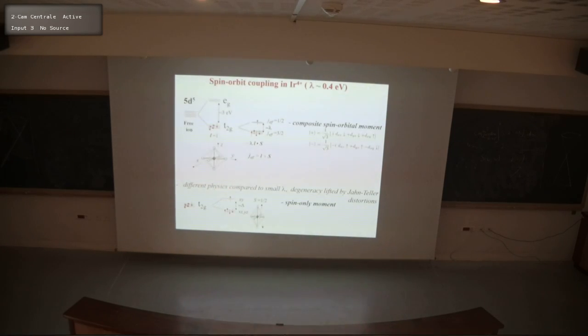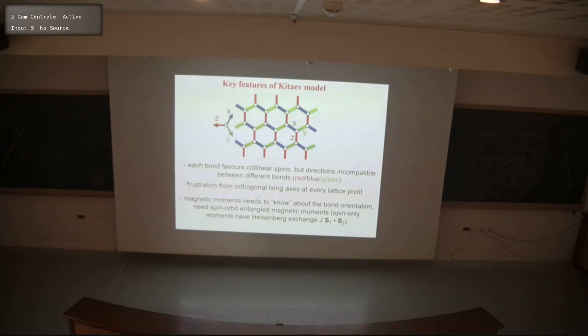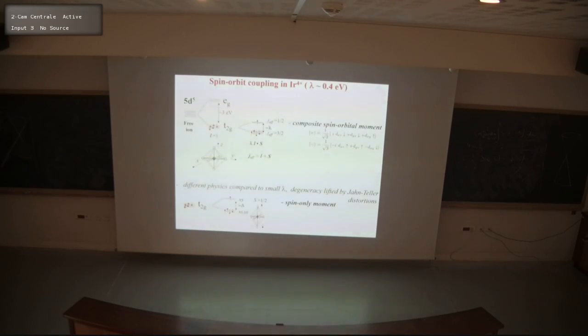So how do we realize the key ingredients to have Ising interactions orthogonal and meeting in a honeycomb arrangement like this? So let's start with reviewing the magnetic ground state of iridium 4+ ions, which is one of the class of ions in materials that are candidates for Kitaev physics. So iridium 4+ has 5 electrons in the d shell. In a free ion, these have spherical symmetry and all the orbitals are degenerate. I'm showing here the one-electron orbitals.